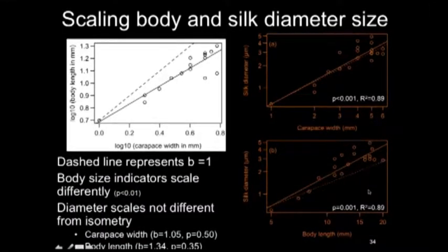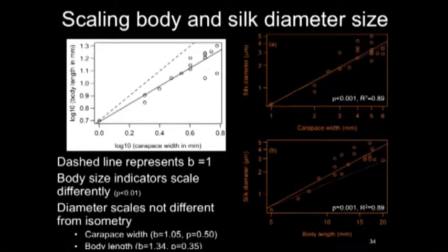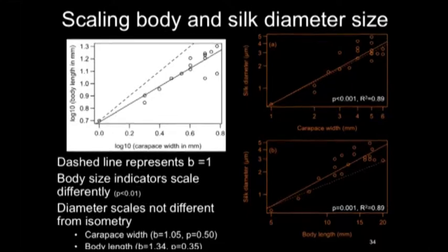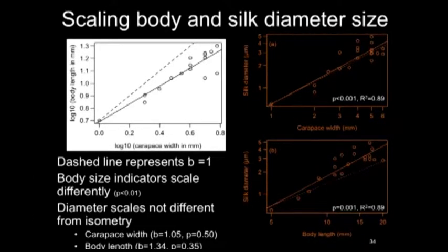So when we measure the diameter, obviously diameter increases, as you can see, this is a measure of spider size, and this is a measure of spider size in carapace width. This is just to be sure that both of those measures could be used in our study, but with diameter, as you can see, it increases, and it did not differ significantly from isometry, which just means that diameter increases at the same rate as body length, body size measurements. So we don't necessarily see anything particularly interesting in terms of the diameter growing faster or slower than the rest of the body.